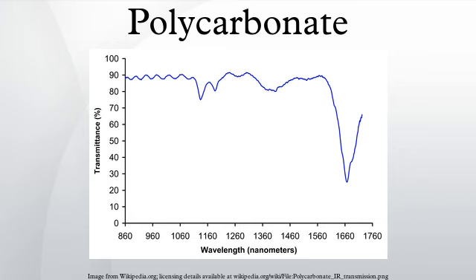Decorative bezels and optical reflectors are commonly made of polycarbonate. Due to its low weight and high impact resistance, polycarbonate is the dominant material for making automotive headlamp lenses. However, automotive headlamps require outer surface coatings because of its low scratch resistance and susceptibility to ultraviolet degradation. The use of polycarbonate in automotive applications is limited to low-stress applications.